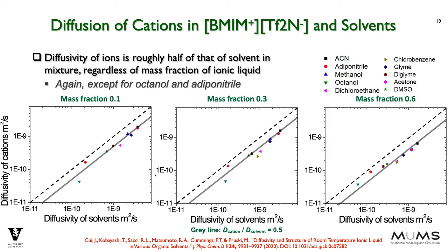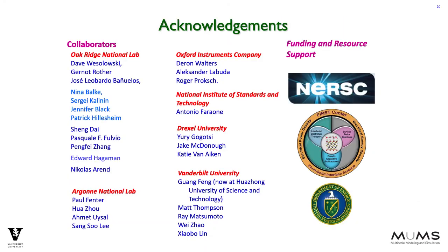Using the experimental data only, but clearly supported by the simulations, these graphs show BMIM diffusivity versus the solvent diffusivity for the 10 solvents at different ionic liquid mass fractions. Strikingly, these results suggested that for 80% of the solvents, the BMIM cation diffusivity is one half that of the solvent, the exceptions being octanol and adiponitrile. This important heuristic, namely that BMIM cation diffusivity is approximately half of the solvent, as a means for choosing an organic solvent, began with purely computational predictions, and so is another example of computational research leading experimental work.